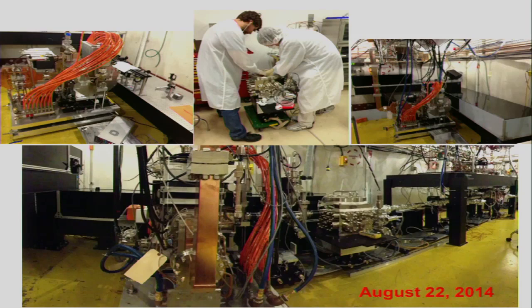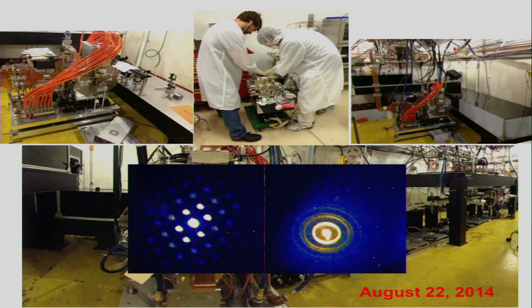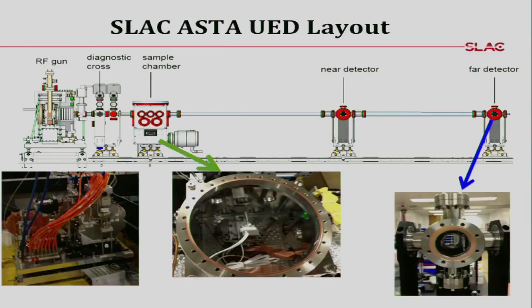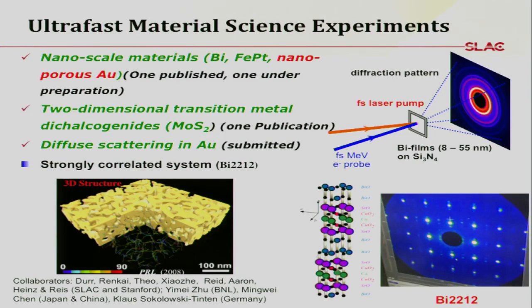And we first installed the optical tables and the photocathode RF guns. We built the sample chambers and completed the commissioning of the UED setup. And on August 22nd last year, we saw our first electron beam. And within a week, we saw diffraction from single crystal gold and polycrystal bismuth. So since then, we have been using this ultrafast electron diffraction to study materials.